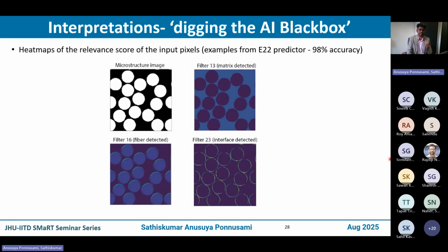And getting into the results, you see on the top left a simple two-phase microstructure. And then what you really see after the digging-in process within the CNN, you see different filters identifying different ingredients or features of the microstructure. For example, in one case, you see on the top right, the matrix phase is detected. Here the fiber phase is detected. Here the interface is detected. So these are the features that are extracted by different filters of the CNN.